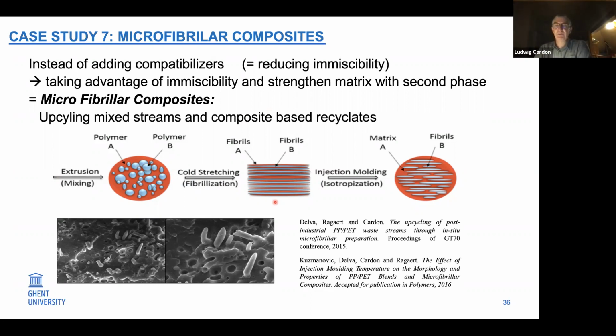We cut that in small pieces, and then we inject at a lower temperature so that our polypropylene will melt, but our PET material will not melt. So by using the right processing parameters and blending strategy, you can create the so-called microfibrillar composites. You can expect immediately that polypropylene and PET do not adhere well, so you have no good adhesion, but you see here the fibrils. And when we can initiate a better adhesion between the PET and the polypropylene, you can create a more impact resistant microfibrillar composite.